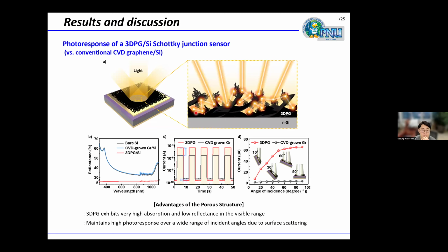The fabricated three-dimensional porous graphene and silicon make a Schottky barrier junction. So we can use this kind of Schottky barrier junction device as a photodetector. As you may expect, porous graphene exhibits very high light absorption with minimal reflection, leading to an effective photo conversion effect. So briefly, we compared the reflectance of porous graphene as shown here. Conventional film type graphene has a high reflectance in this system. But when we form the porous carbon material on the silicon, the overall surface reflectance is decreased to under 10%.